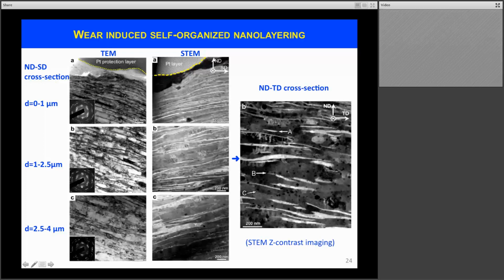So in fact, here we have a panel of TEM and STEM micrographs. On the left, it's more like the structural characterization of the microstructure. On the right, the middle column, it's more the chemistry. And here we're looking down away from the wear surface. We see that this nanolayering extends over several microns.